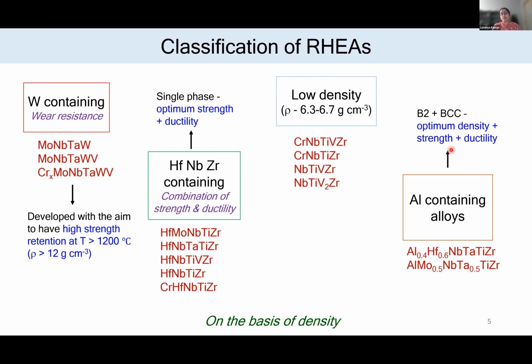And finally, to further reduce the density of the alloy, people added chromium, titanium, and vanadium. When the addition of chromium and vanadium happened, it led to the formation of Laves phase. Although it increased the strength, there was a drawback in terms of ductility. These alloys were very brittle.